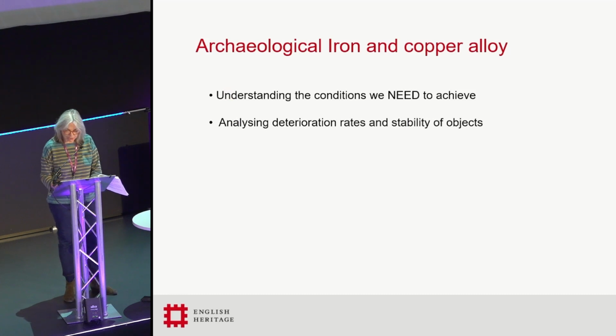Oxygen consumption measurements have been applied to both iron and copper alloy artifacts to measure and predict their reactivity at varying relative humidities. When iron or copper alloys corrode, the fuel in that process is oxygen. So if we can measure the oxygen that is being used up, it gives us a good idea of how quickly the object is corroding. These analyses have allowed us to safely display non-reactive material without low humidity control and to guide the strategy needed for the most vulnerable material.